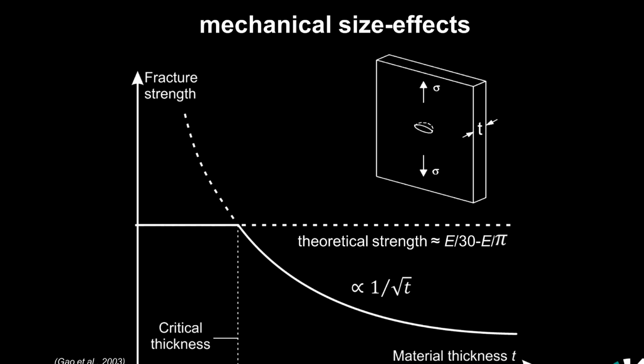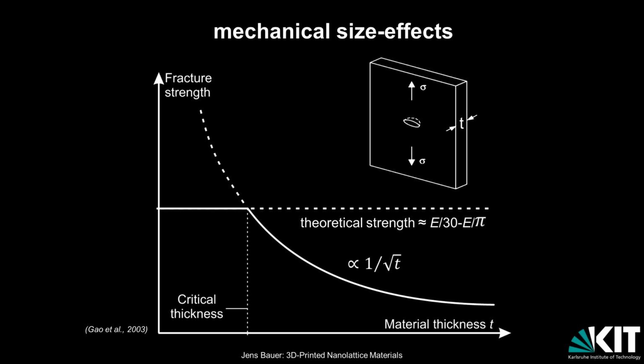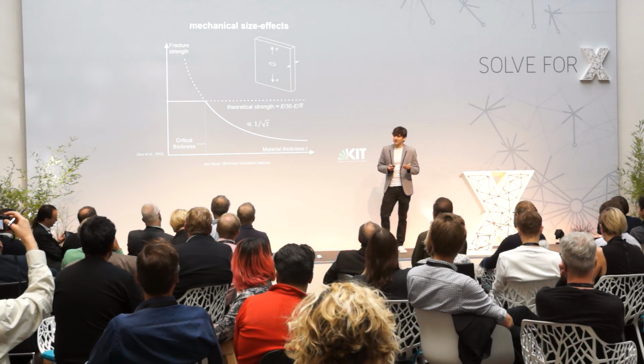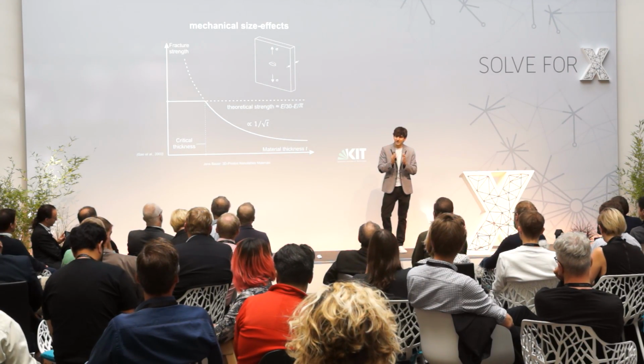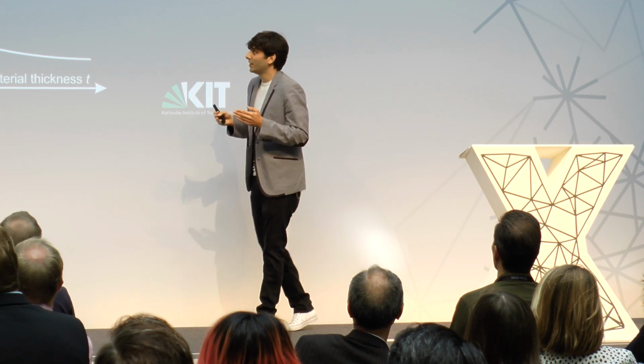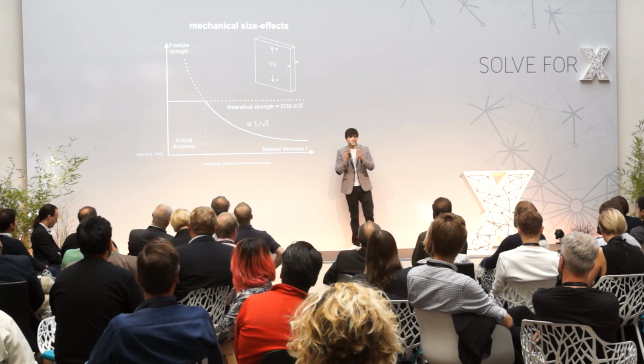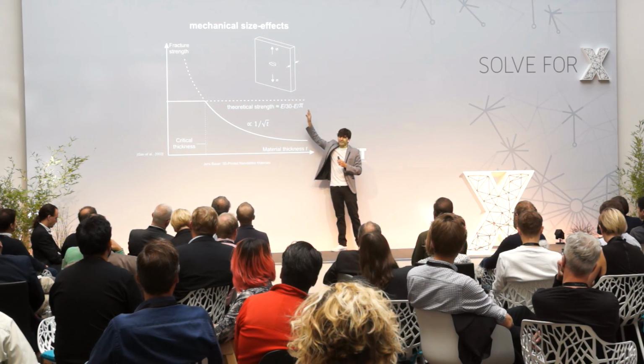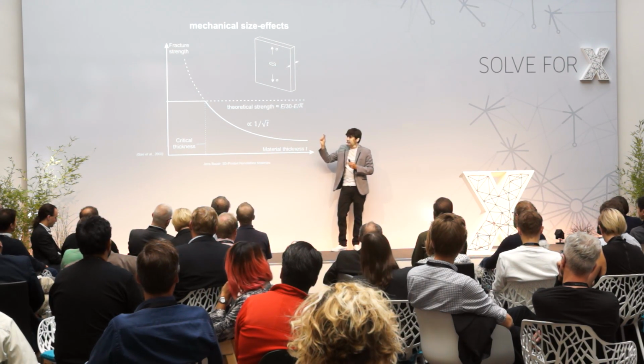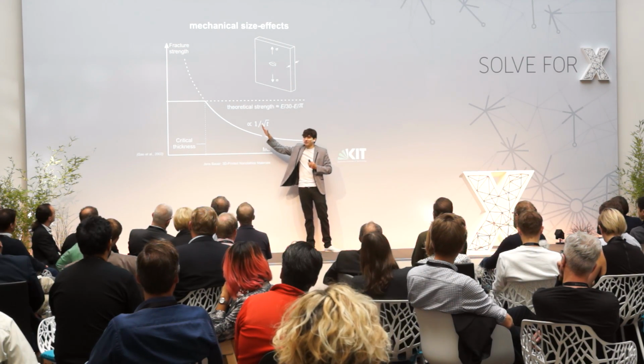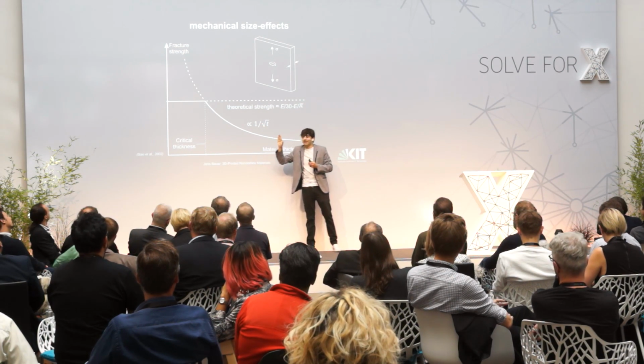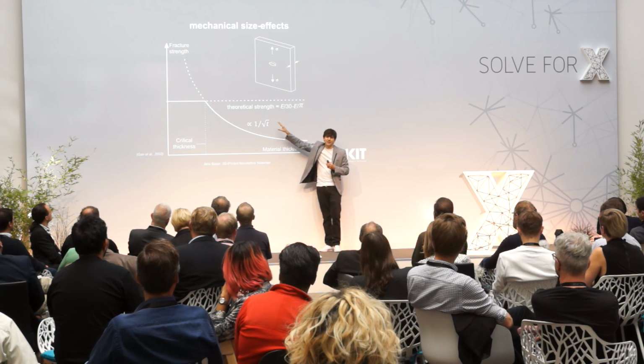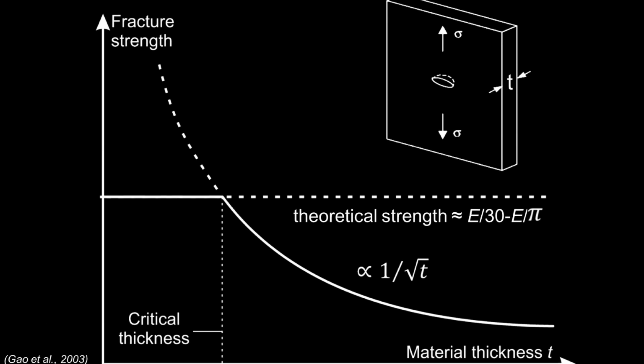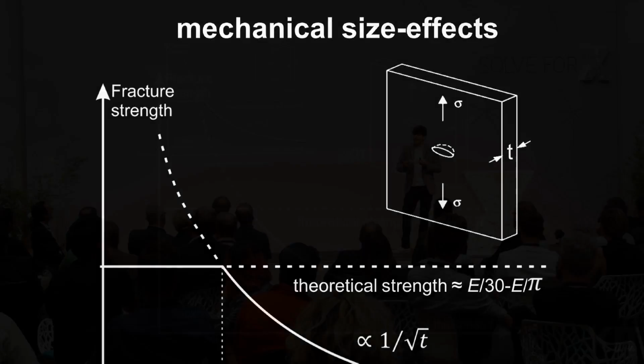The fracture strength of brittle materials such as ceramics usually scales with the size of flaws which those materials contain. The smaller the flaws, the higher the strength. Now the flaws themselves scale with the overall dimensions of an object. So that means for that plate over here, when we make it thinner and thinner in the nanometer scale, the strength increases rapidly and eventually reaches the theoretical strength below a certain critical thickness, which is assumed to be in the range of a few nanometers.